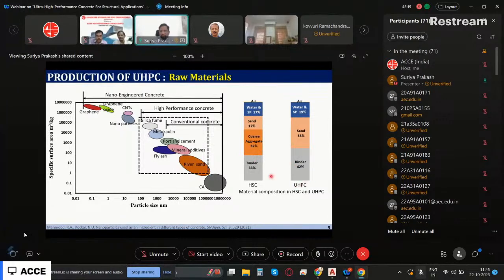But if you look at UHPC, the binder obviously will increase. But you see that there is no coarse aggregate at all. Coarse aggregate becomes zero, and we use only fine aggregate, and that is about 38%. In fact, with this regime, particle size ranges from about 20 to 30 nanometer to almost up to 1 millimeter. This is the range our particle sizes are going to be in ultra high performance concrete. We are going to use a lot of silica fume, a lot of cementitious system, Portland cement, fly ash, and then we can also use GGBS and so on. Okay, so there is no coarse aggregate in UHPC.